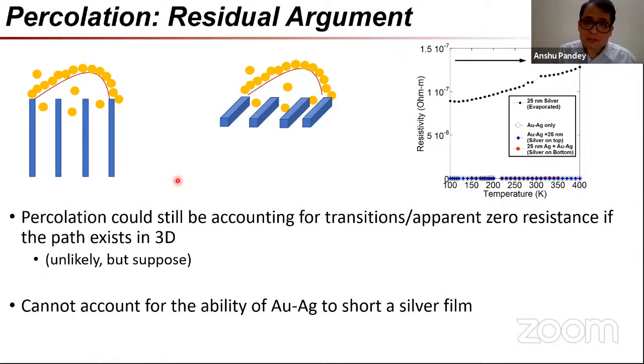So that apart, one residual argument from percolation might still stand, even though the critical current exists, which is: what if we had a path following 3 dimensions rather than 2? This becomes very hard in a 2-dimensional film, which is very flat. But nonetheless, if this existed, I would still, with a simple mind, point to the older data way back from 2018, where we showed that AuAg can actually short out a silver film. Because with that ability, it's hard for me to imagine a 3D bridge being able to disconnect the voltage leads. And even if such a bridge actually does disconnect, that would still imply that the bridge presumably at least has a lower resistance than silver, which is again all we are trying to say here.